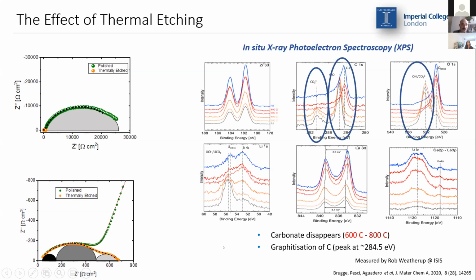What we concluded from this experiment is that, to start with, the polished sample has a layer of lithium carbonate that sits on top of the LLZO. This obviously creates a more resistive interface in contact with the lithium metal. However, upon heating up, we remove the layer of lithium carbonate and we improve the contact between electrode and electrolyte.